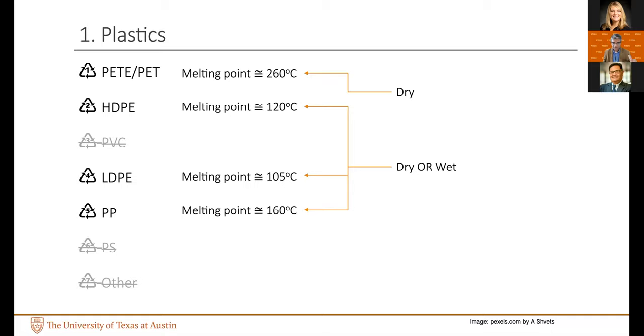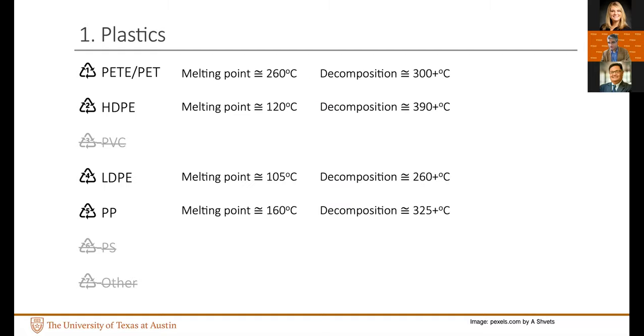And when it comes to other plastics, HDPE, LDPE, and polypropylene, you could add them during mixture production in a dry process, or because the temperatures are within the range of mixing with asphalt binder, you could blend them with the asphalt binder. Blending in the wet process also gives you the advantage that you could use compatibilizers and other agents. Another thing to keep in mind is the decomposition temperature. Again, there is no one HDPE. HDPE is just a family of plastics. LDPE is also a family of plastics and so forth. But generally speaking, the decomposition temperature, the temperature above which these plastics start to degrade, is in the range of about 260 to 300, 400 degrees Celsius. So this is good because these two temperatures tell us the viability of using these four categories of plastics with asphalt mixtures. And the others we have excluded for reasons that I've discussed before.